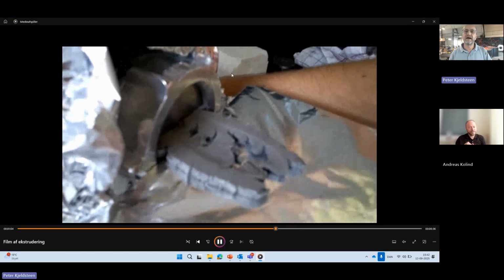And in fact, it was a problem for the meat grinder to do this task because the agar system has a glass phase that solidifies at around 65 degrees C. So we needed to heat up to above 65 degrees. We were running all this process at about 70 degrees, so we had heating elements on the meat grinder. And the meat grinder was not really made to run at this temperature. So it lasted for 3 days. But we got some very good results.